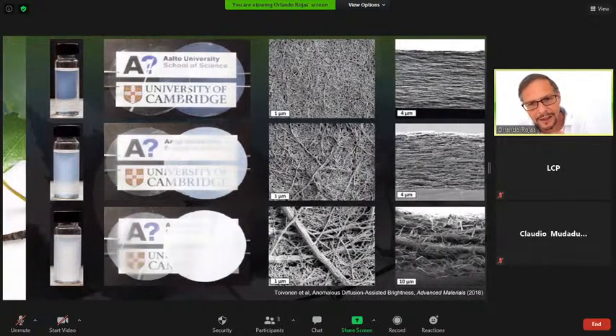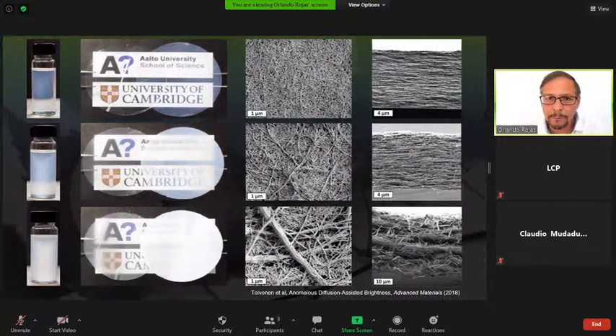separating the nanocellulose by different sizes, as you can see in the middle of this figure, that is a work in collaboration with Cambridge, Silvia Vignolini, and my colleague in Finland, Olli Ikkala, and their students. Here you can see how we are able to separate nanocellulose in different lateral sizes, and from those produce nanopapers. And those nanopapers will have different degrees of transparency. And the explanation for that opacity or the opposite, transparency, has to do with the porosity of the material, based on what we know in paper making.